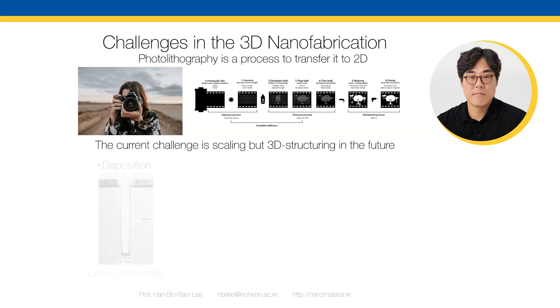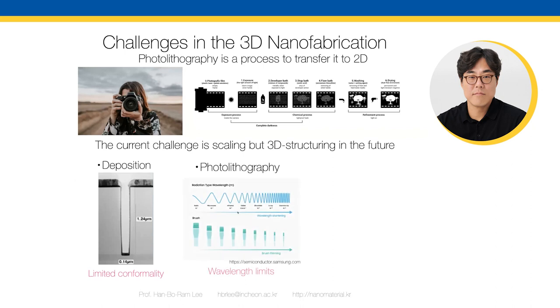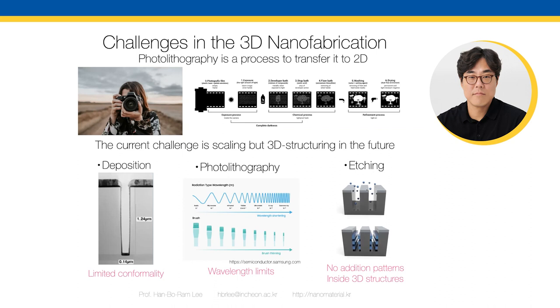The current challenges are: first, it is very difficult to deposit thin films inside 3D structures because of limited conformality. Second, photolithography pattern size strongly depends on wavelength — we use shorter and shorter wavelength laser sources, but still have wavelength limits. Third, conventional etching is isotropic, but we now need to make additional patterns inside 3D structures that cannot be made with conventional etching technology. Despite all these challenges, there are many customers for new silicon chips, so we must keep researching and developing these processes.